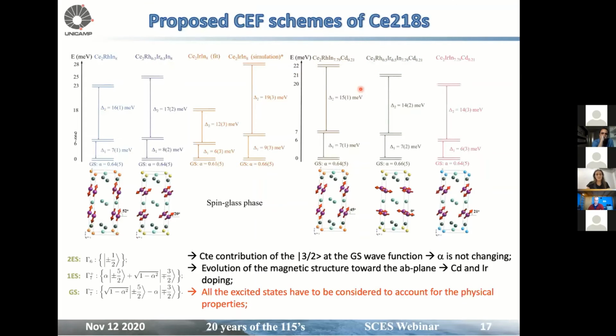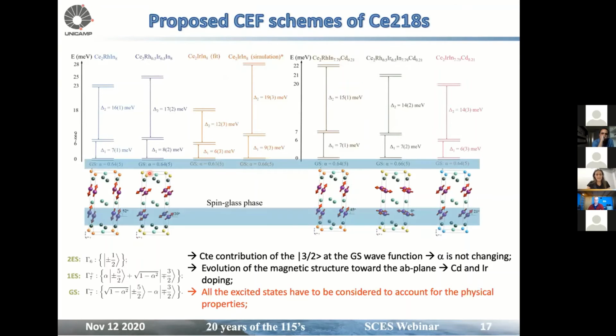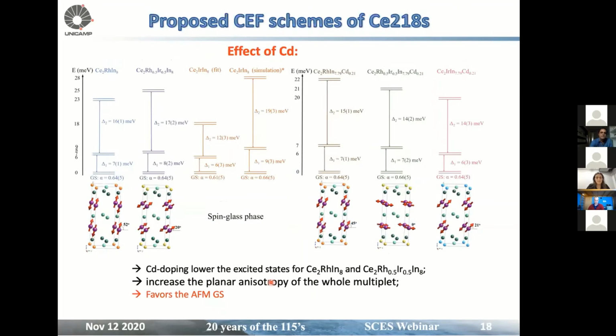So those are all the crystal field splittings that she found. And we can see that as alpha of the 5 halves is not changing so much, it suggests that we have a constant contribution of the 3 halves state in the ground state functions, because alpha is not changing much. However, we still have an evolution of the magnetic structure toward the AB plane for both cadmium and iridium doping. So that means that all the excited states have to be considered to account for the physical properties. So the overall effect of cadmium, for both the rhodium member and the rhodium half, iridium half, is that cadmium is lowering the excited states for both members, and that increases the planar anisotropy of the J5 halves, and then that favors the antiferromagnetic ground state.